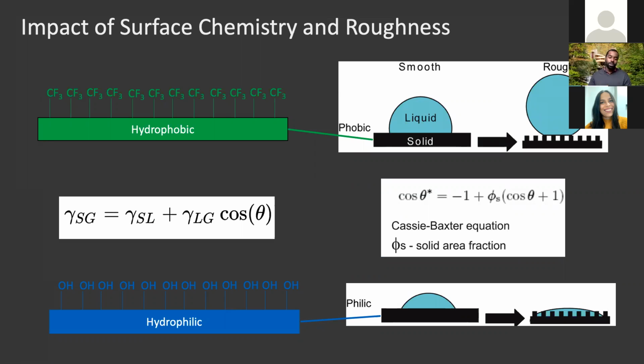But if you were to clean that surface and then maybe functionalize it by putting something like an OH group, so maybe metal hydroxyl kind of bonds on the surface. You could do this through plasma cleaning or various other ways, silanization. Then you can change a surface that was hydrophobic into a surface that's hydrophilic. And this again is described and captured by Young's equation. These are for ideal surfaces, and surfaces are frequently not ideal.